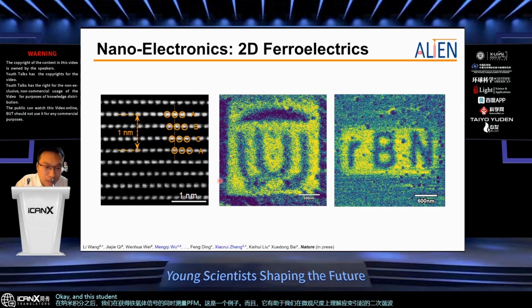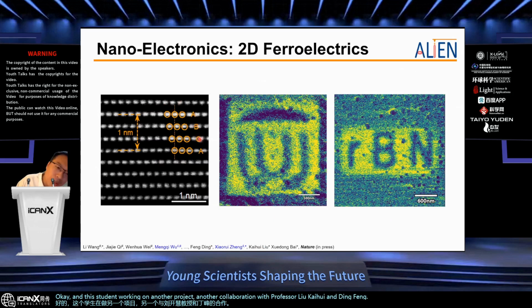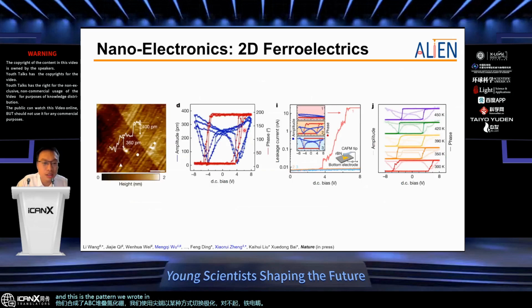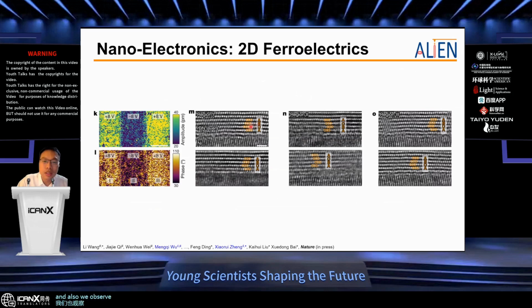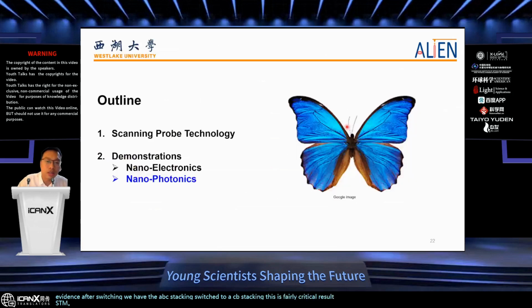Okay, and this student is working on another project, another collaboration with Xuedong Bai and Professor Liu Kaihui and Ding Feng in Beijing. They synthesize ABC stacking boron nitride, and we use the tip to switch the polarization, the ferroelectric domain of the HBN, and this is the pattern we wrote using scanning probe microscope. I'm going to skip a few slides, but this is a PFM characterization to prove this domain switching is real. And also, we observe the STM evidence. After switching, we have the ABC stacking switched to ACB stacking. This is a fairly critical result to prove the switching is real.